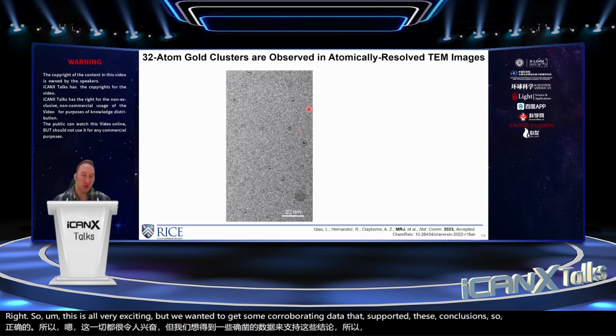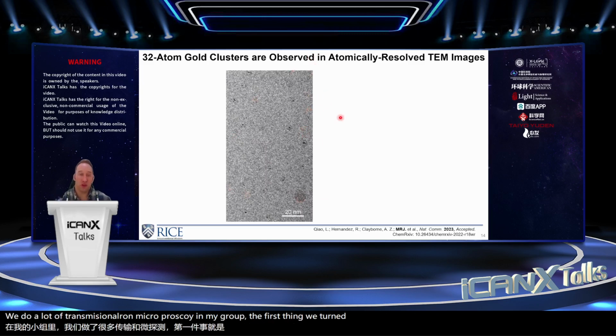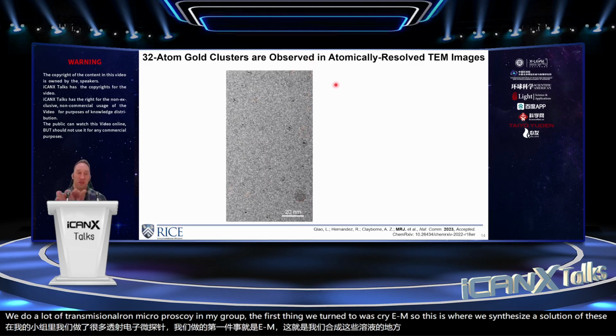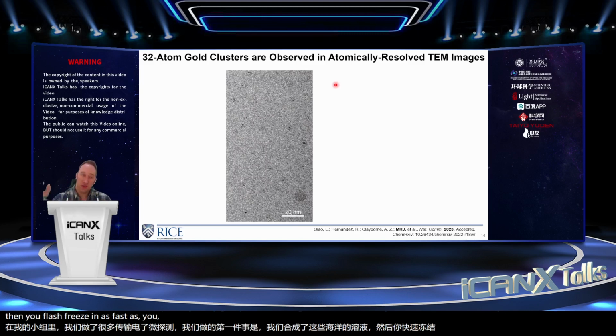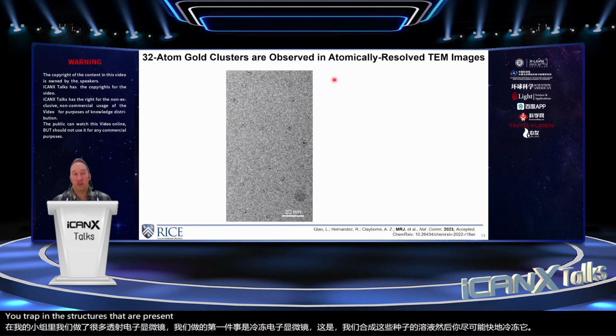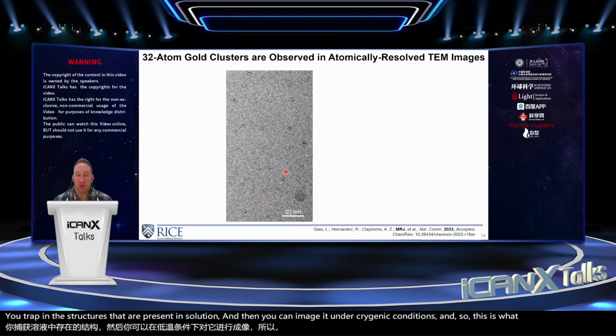We do a lot of transmission electron microscopy in my group. The first thing we turned to was cryo-EM. This is where we synthesize a solution of these seeds, then you flash freeze it as fast as you can. You trap in the structures that are present in solution, and then you can image it under cryogenic conditions. And this is what one of those images looks like.